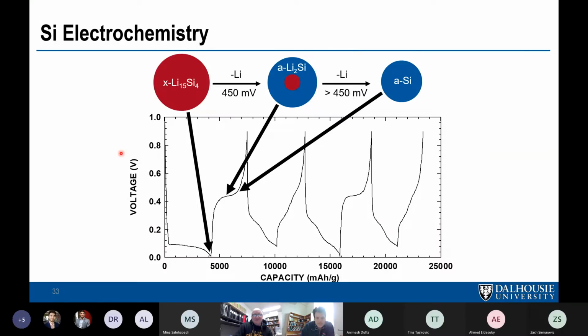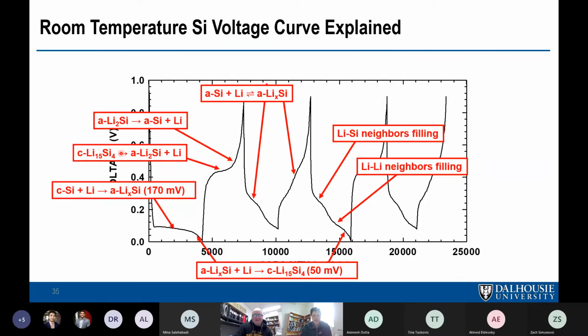This is where we ended last time, right here with the electrochemistry of silicon. And so we went through this. It lithiates in a 2-phase region, and you make Li15Si4, and that delithiates in a 2-phase region. Then you get these single-phase regions, and if you're careful in your cycling limits, your voltage limits, you can stay in the single-phase regions for cycling. But if you go below 50 millivolts, you instantaneously crystallize the Li15Si4 phase, and it's hidden here. But you get another plateau that's identical to this one, and you're in a 2-phase region again.